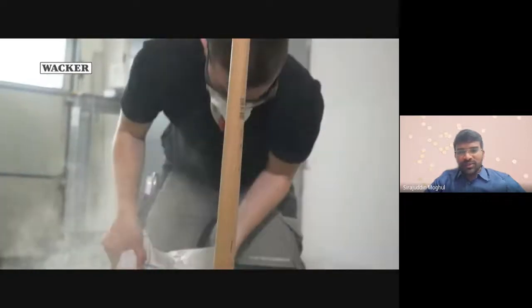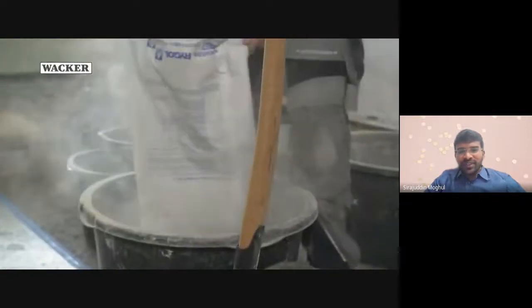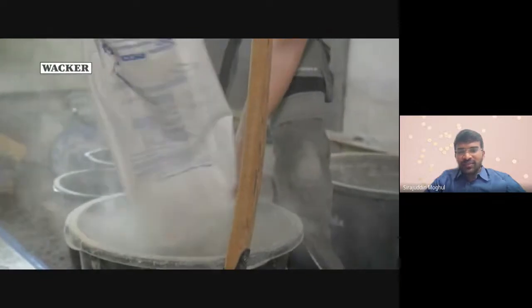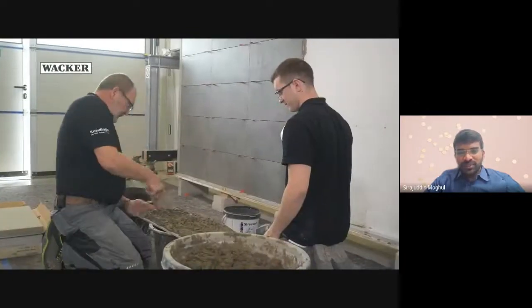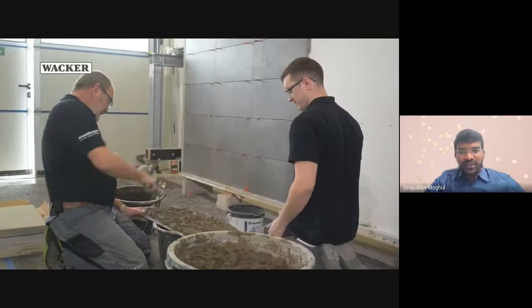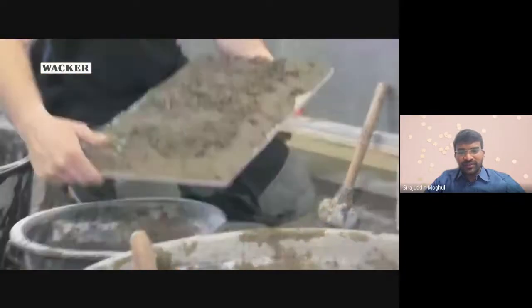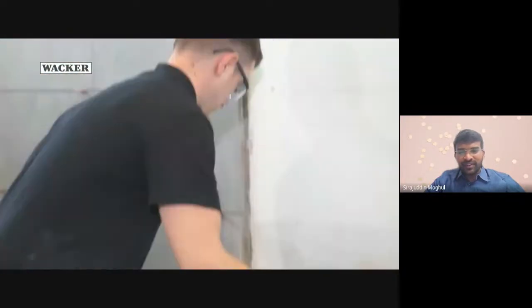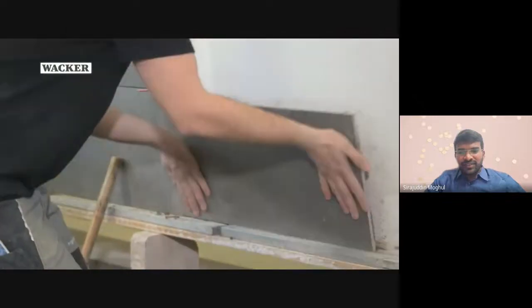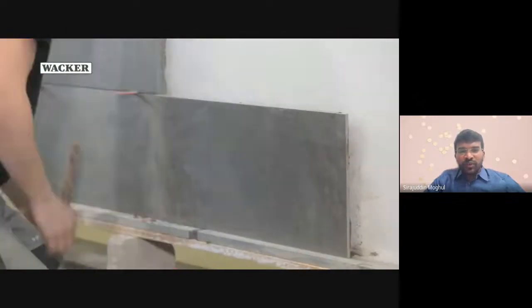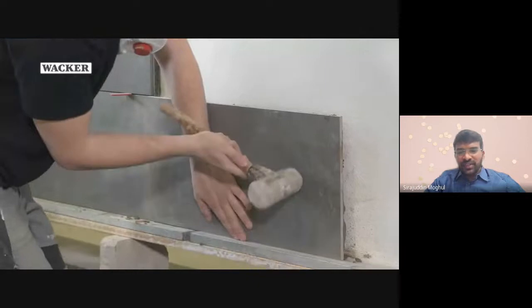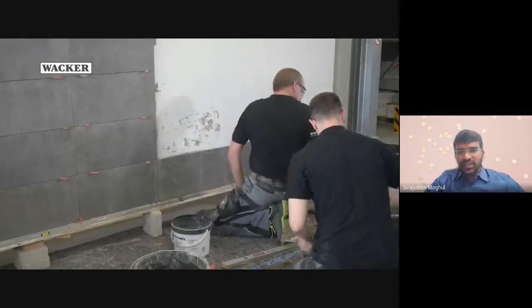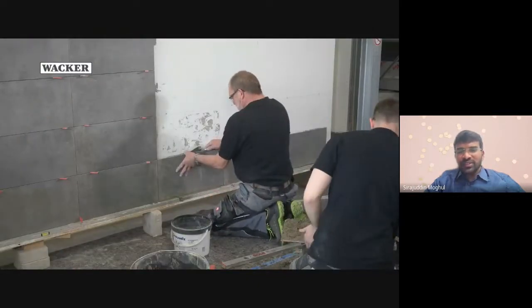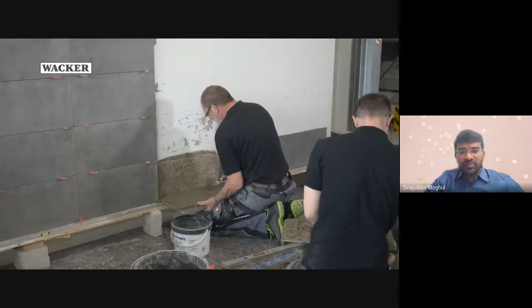how much cement to use. It doesn't come in bags, so people use random cement and sand, and then you try to fix it on the tile, while another presses the tile against the wall to bond it in place. The key factor in the thick bed method is constant adjustment. You would have noticed how much easier the other method is, and how much material is being used if it is thick bed mortar.